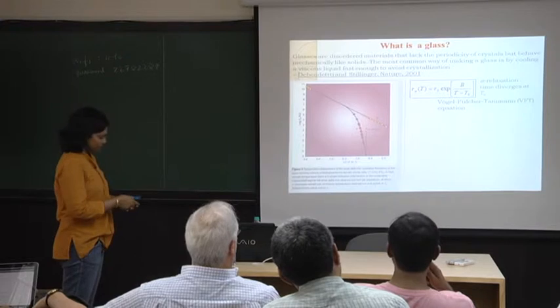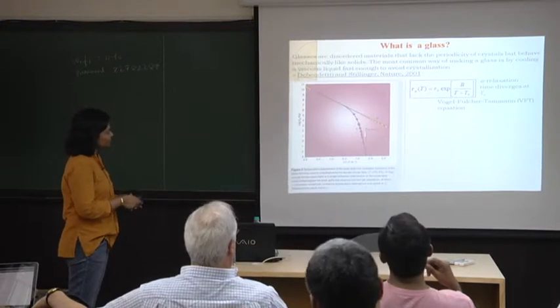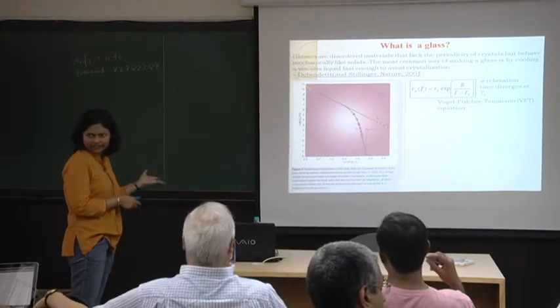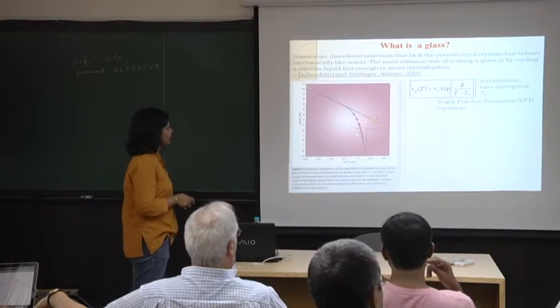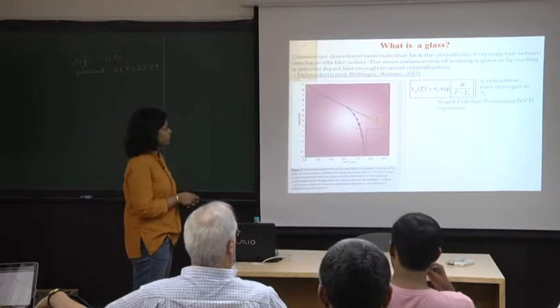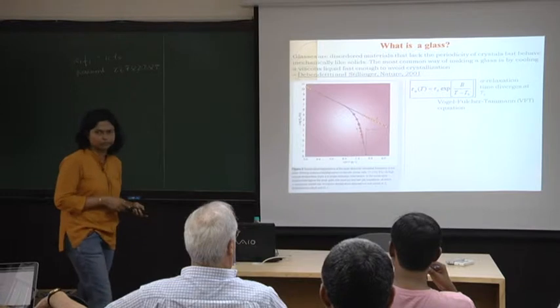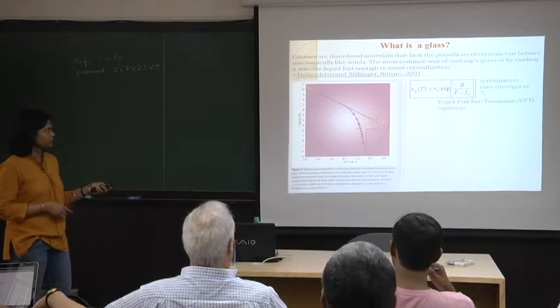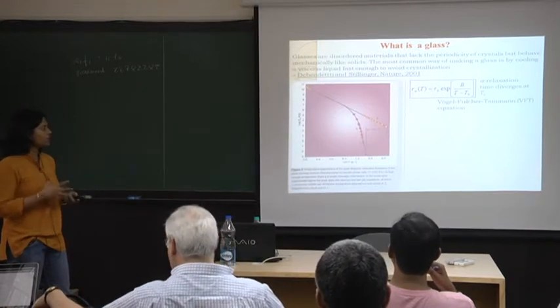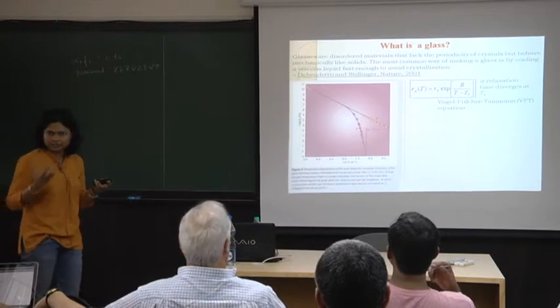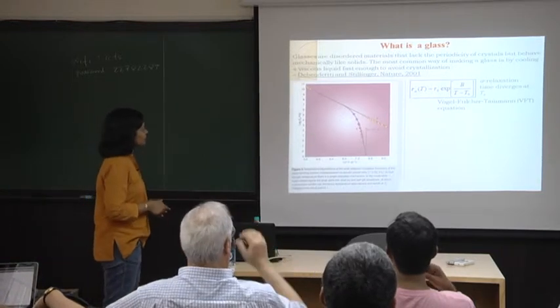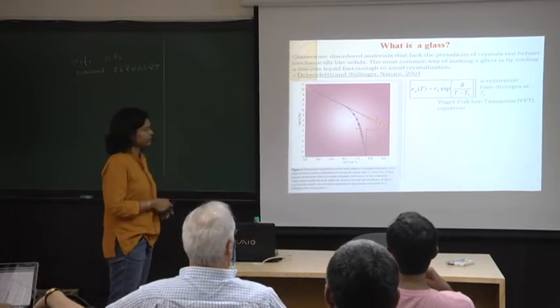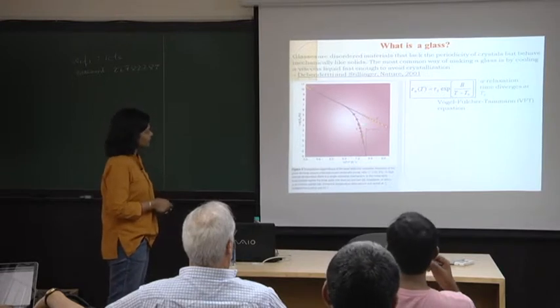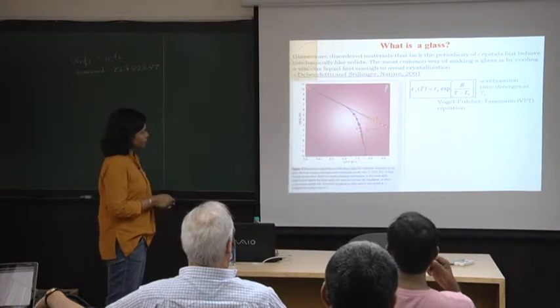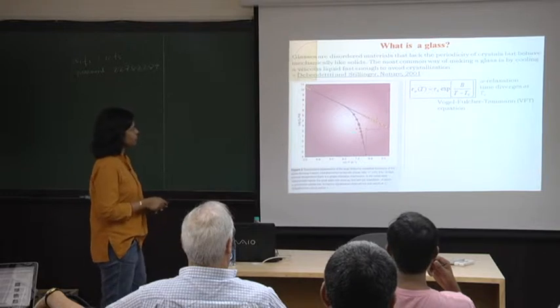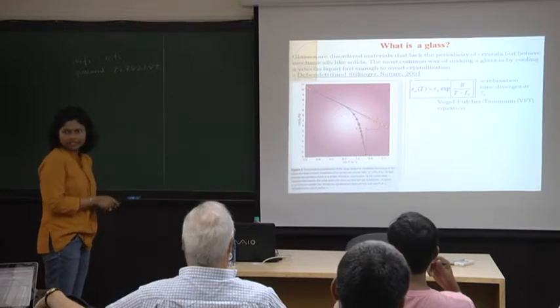Yeah, it's old. So, okay, here, of course, this is the alpha relaxation process, which is basically the slower relaxation process, slower than the beta relaxation process. The beta relaxation process corresponds to particles rattling within their cages, and this is basically particles diffusing out of their cages. And this slow relaxation process, the relaxation time for the slow relaxation process, you can define like this.